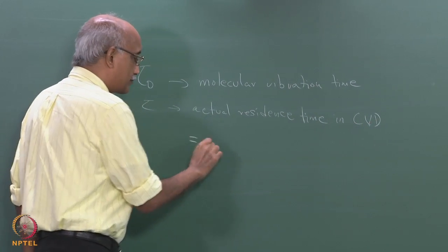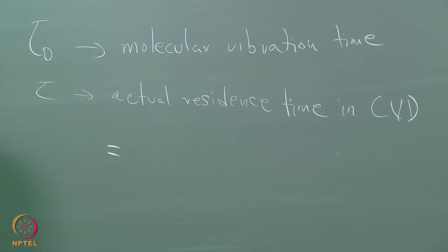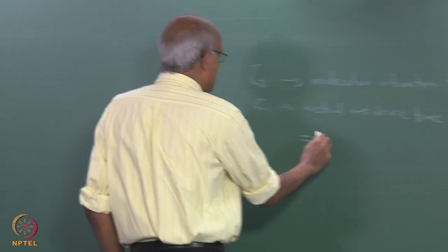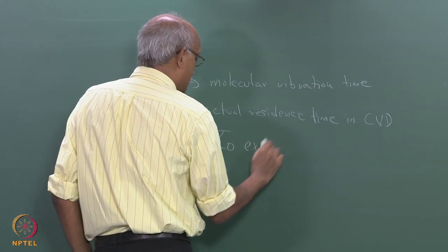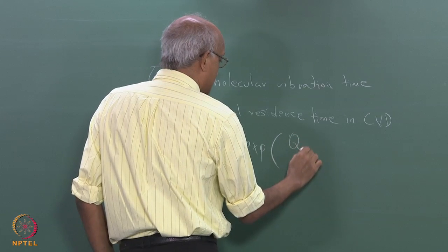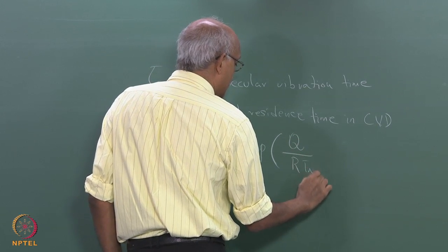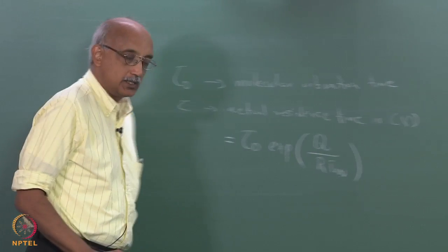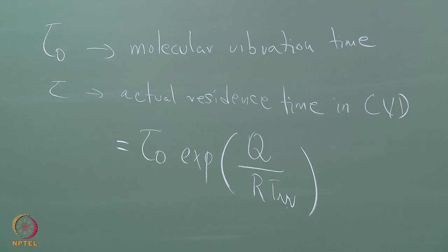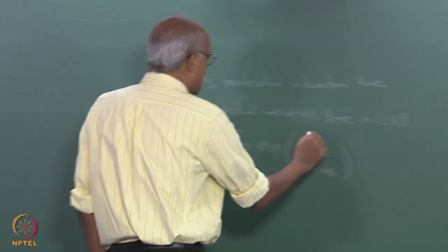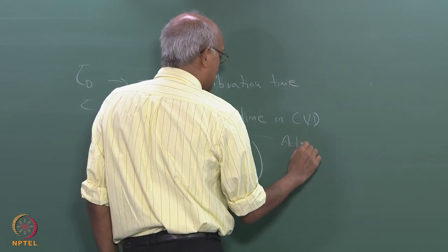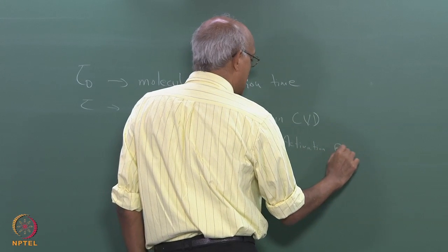in CVD, which is essentially chemically enhanced, there is a heterogeneous chemical reaction that is going to bind the molecule to the surface, which means it is not going to leave as quickly. It is going to stay at the surface longer, and that is given by tau 0 times exponential of some Q over R T_w, where T_w is the temperature of the substrate, and Q is an activation energy